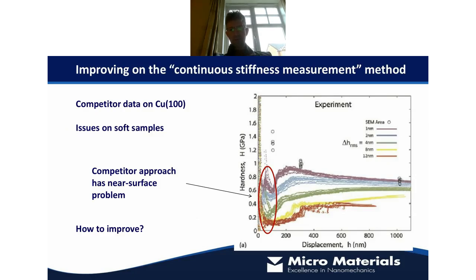And the last thing I wanted to say was something about continuous stiffness measurements. It's not my usual approach to criticize competitor data, but this image on the right is still quite an important figure, because this paper is still referenced by the standard as potentially the best approach to try and mitigate the problems with the continuous stiffness measurement. And in the upcoming standard at the moment, it says if you minimize that oscillation amplitude, you can minimize the problems on soft samples.